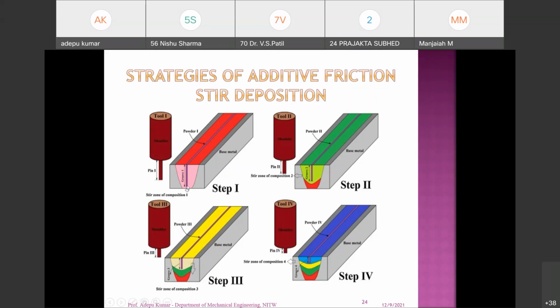Initially, what we do is make a groove and fill it with reinforcement particles, let us say silicon carbide, then apply the processing. Then you can see this red region is a composite material, a mixture of the virgin material and the reinforcement material. Then again you make a groove, fill the powder, and apply the process. Then you get the second green region.